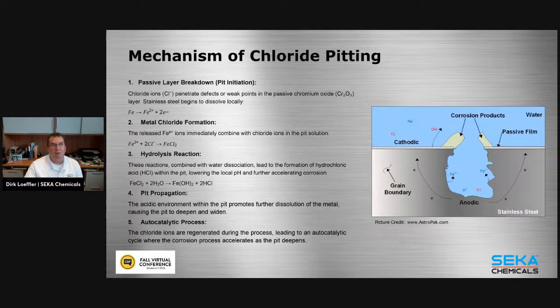Again, we're flying through this because of time, but you see here the chloride ions penetrate, metal chloride formation, hydrolysis creates our hydrochloric acid. Because we now have hydrochloric acid in the pit, the pit keeps getting deeper and worse and worse. Now we have our pit propagation. And again, this is what we call an autocatalytic process. That means it'll just keep regenerating itself into more chlorides, and then the whole process starts over. So this is just going to get worse and worse, and it's an ongoing process.